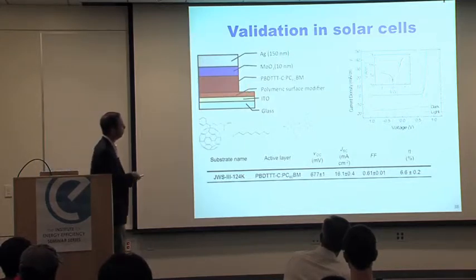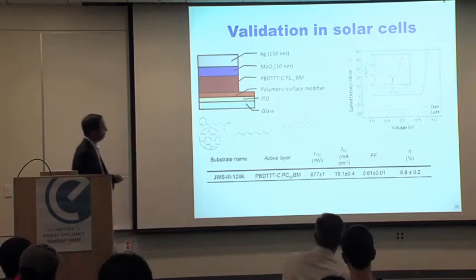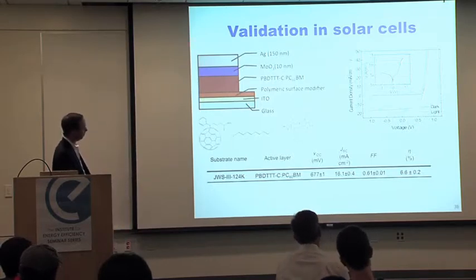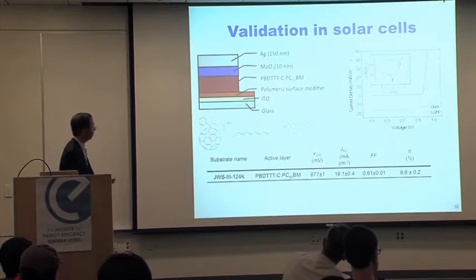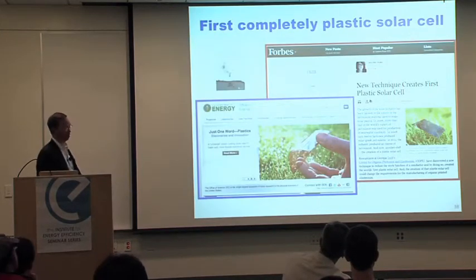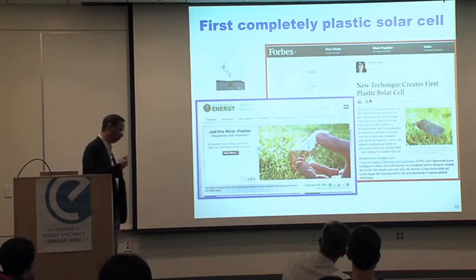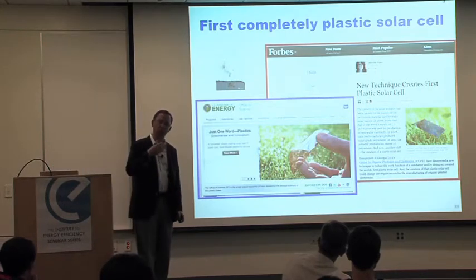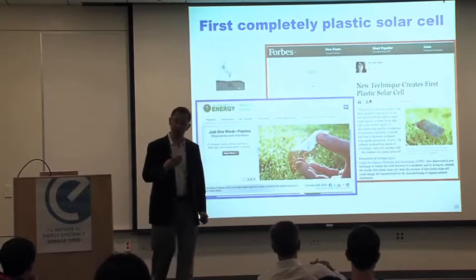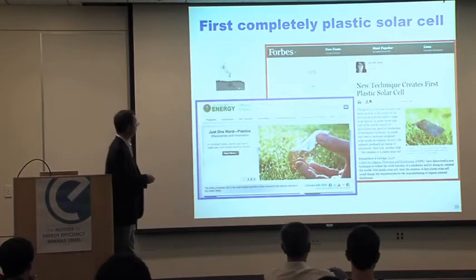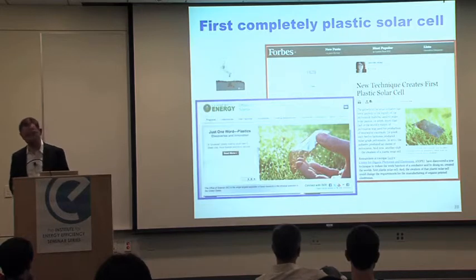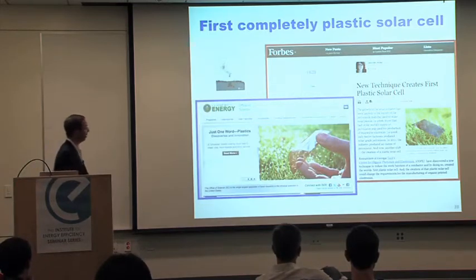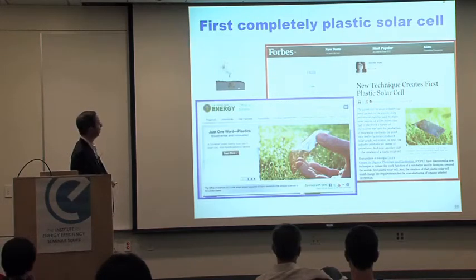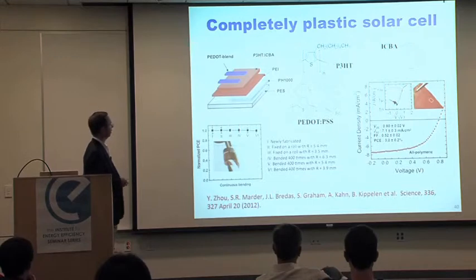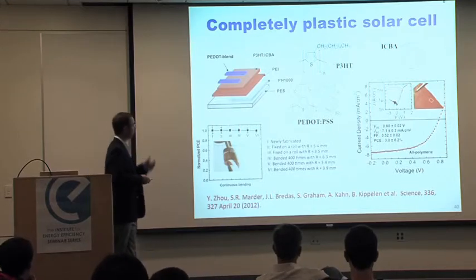And so, sure enough, you can get fairly good solar cells, okay? Fairly good efficiency here, okay? Now, remember I showed you that you can use that modification to also lower the work function of conducting polymers. And so we could make low work function conducting polymers, and that enabled us to fabricate a solar cell where all the layers were actually made from organic, completely plastic layers.